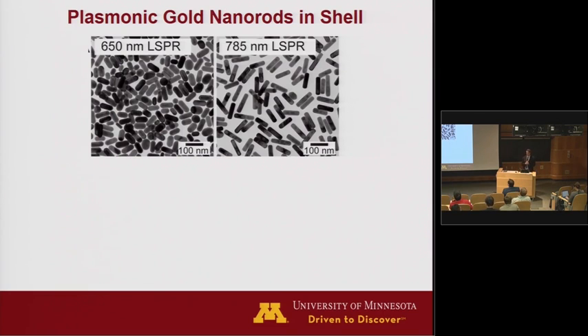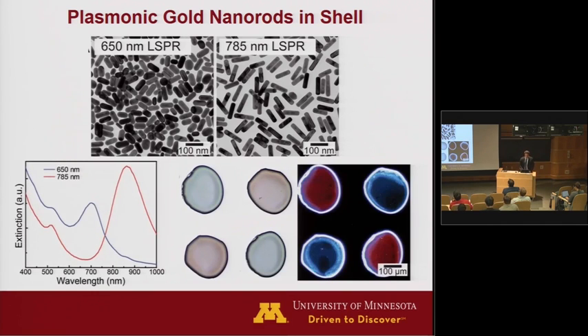They have the same diameter, but they have two different lengths, a short rod and a long rod. And they have two different resonance peaks here. So this is the peak that's determined by the diameter of the rods, and then they have two different lengths, so the peaks here are shifted one from the other between these two rods in terms of the absorbance spectrum.